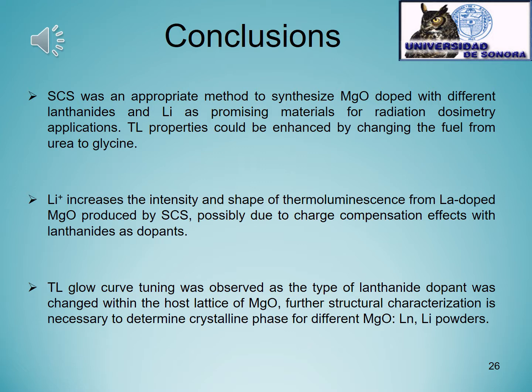The TL glow curve tuning was observed as the type of lanthanide dopant was changed within the host lattice of magnesium oxide. But further structural characterization is necessary to determine crystalline phase for different magnesium oxide, lanthanide, lithium powders.